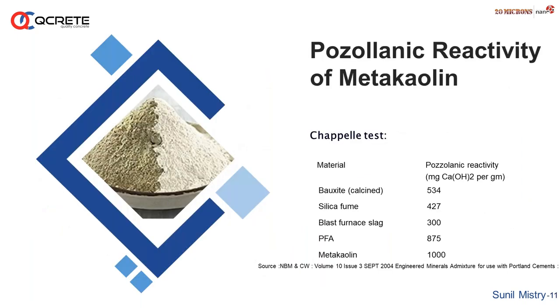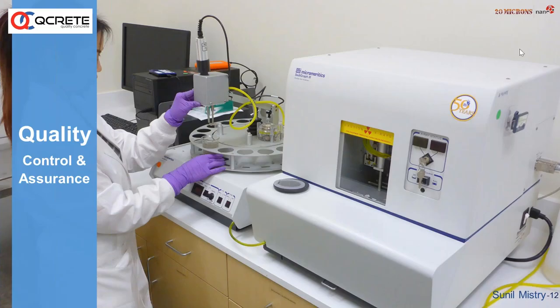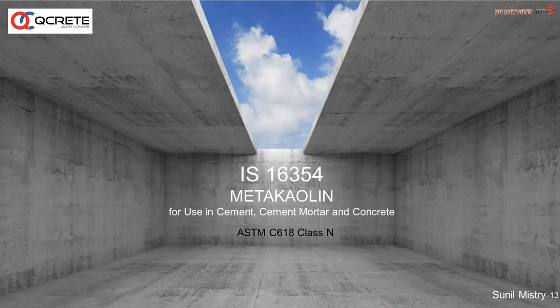As I explained, metakaolin has almost 96 to 97% reactive compound, in combination of meta silica and alumina. The screen shows that metakaolin has a pozzolanic reactivity of more than 1000. Here it is a source, and the Chapelle test is there. These are the R&D part, and quality control is a must right from raw material to the finished goods.